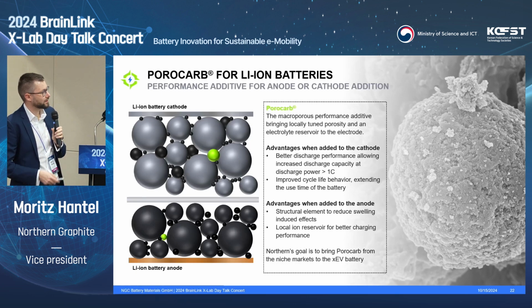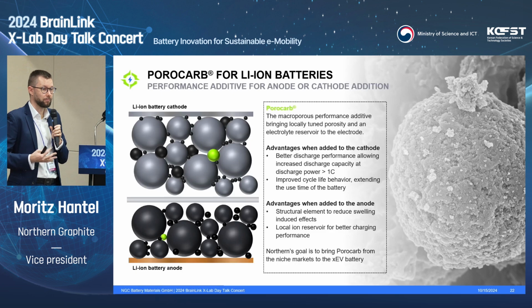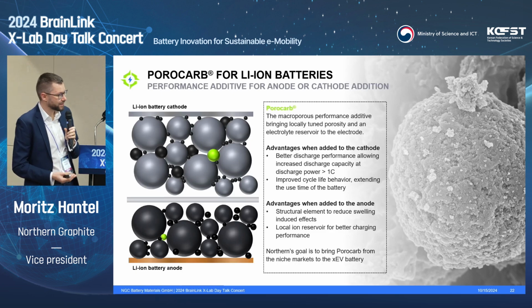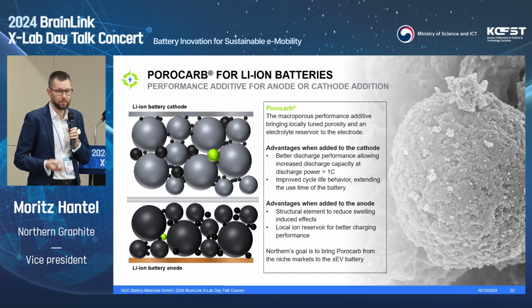Now looking more at a classic system, you can apply porocarb in a carbon mix either on the cathode side or the anode side or both. In the end, it's always important to have it in a carbon mix, meaning you have a classical carbon conductive additive like acetylene black, carbon black, or CNT, and you add porocarb to the mix to enhance the ionic component.